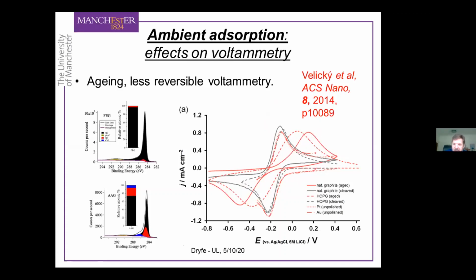You see the effect of aging. That's for natural graphite, and you see the same effect for HOPG, which is a synthetic graphite. You see the grey dashed line, a fairly reversible CV, and the red dashed line, a much less reversible CV, if you let the material age, i.e. if you let these organic contaminants adsorb on the basal plane of the graphite.